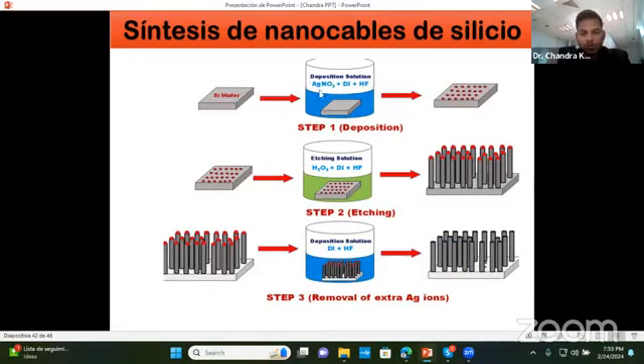We can dip the silicon inside a beaker where we have a solution of the precursor AgNO3, and we can deposit silver. Later we put this in a mixing solution of H2O2 plus HF, and we get the etched structure. Later we can remove the silver, and in the next step we use HF, hydrogen fluoride, to eliminate the oxide or nitride layer which is present here.